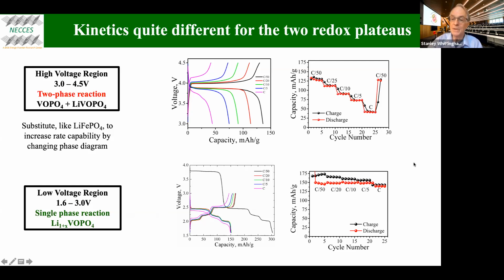But we do have challenges in this material. At high rates, the coulombic efficiency is very good. So we get out the same number of coulombs we put in. But at low rates, we're putting more in than we get out, but we're getting the theoretical amount out. And I should emphasize, in these materials, we have got the theoretical capacity. So on charge, we're getting another reaction going on. And we now know this is the vanadium phosphate electrocatalytically oxidizing the organic solvent. And there are some protons going into the lattice, which are then evolved. So we've got an oxidation reaction going on here. It doesn't damage the cathode at all, but clearly is not a viable approach going forward. So we have to solve two problems to make this material viable. One is the high rate capacity at the high voltage, and the other is these side reactions. So we're looking at different solvents to do this.